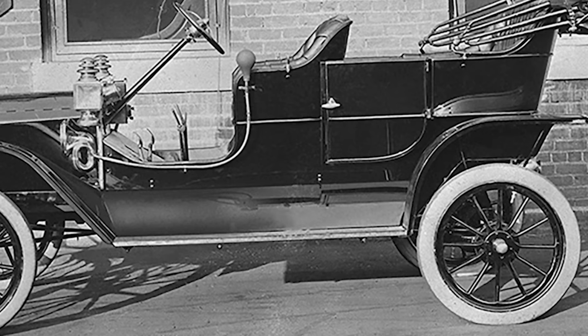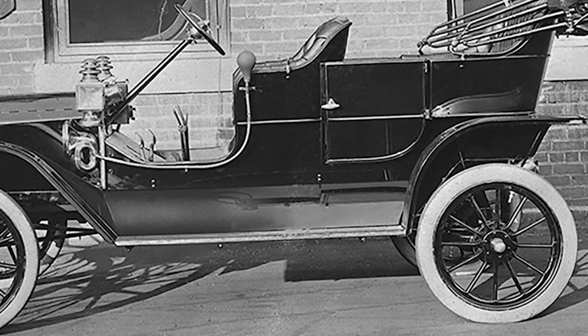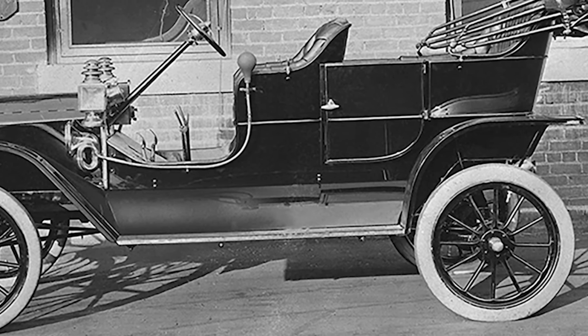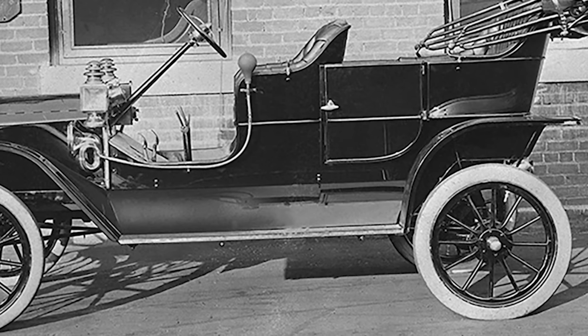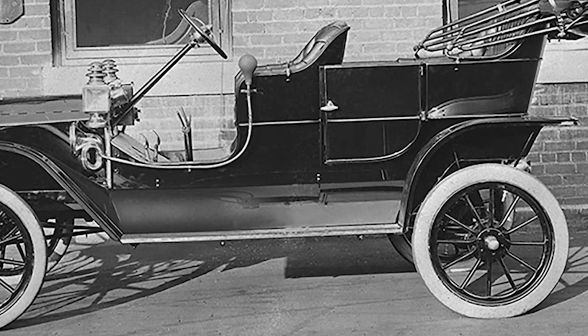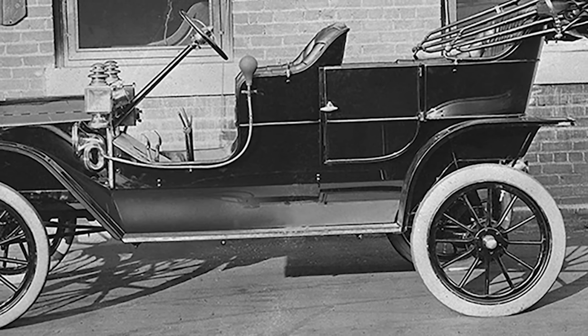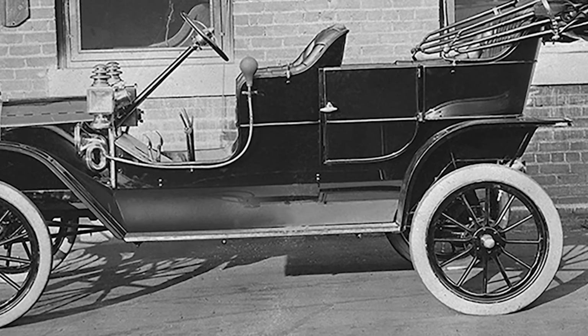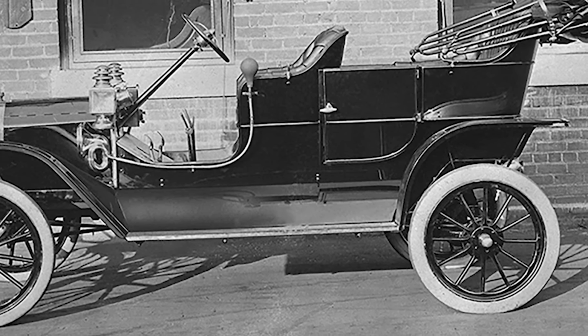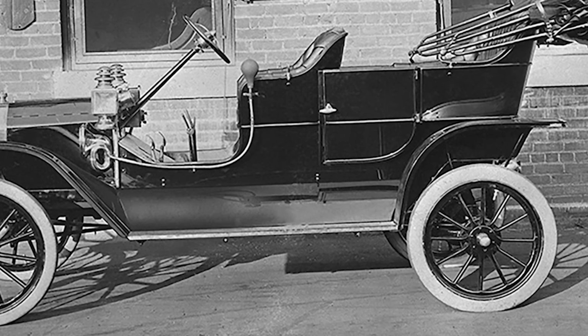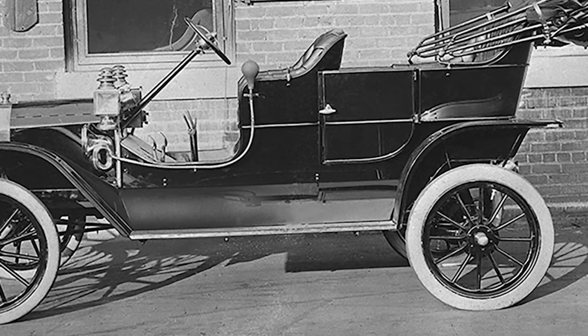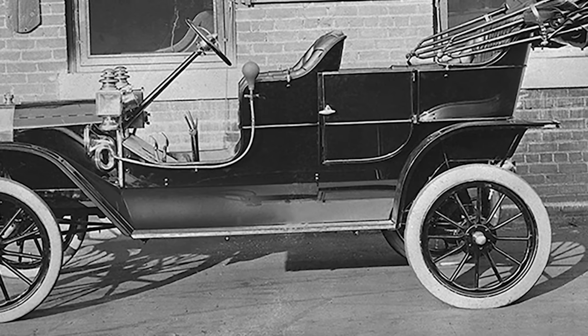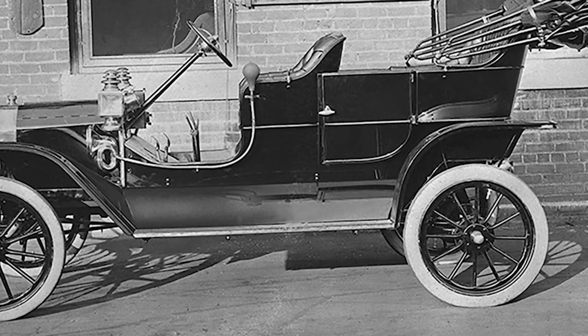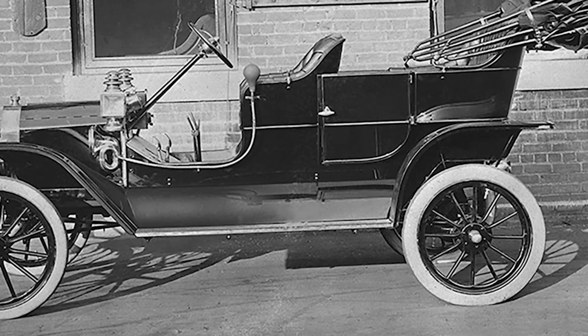Then disaster struck. The extreme heat turned most of the vanadium into worthless slag, leaving behind steel that contained less than 0.1% vanadium, not enough to matter. What little metal emerged from the crucible demonstrated none of the flexibility and strength that Ford had witnessed in the French valve stem. Republic had successfully reached 3,000 degrees, but the metallurgy remained beyond their understanding.